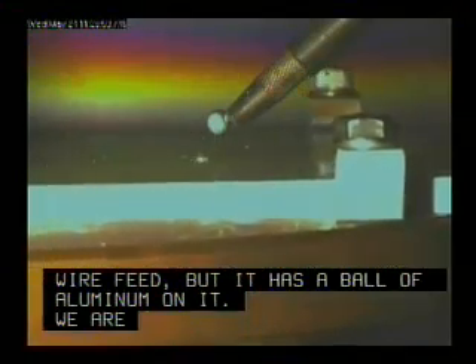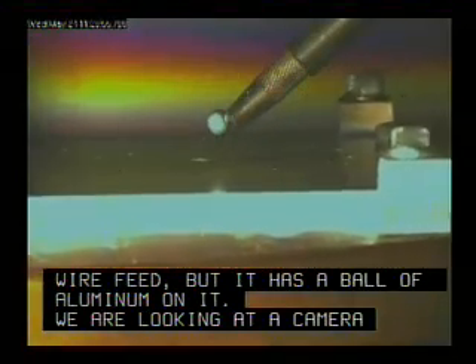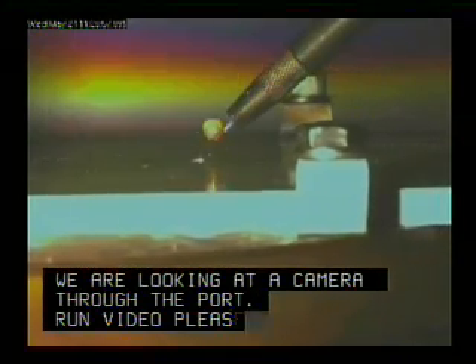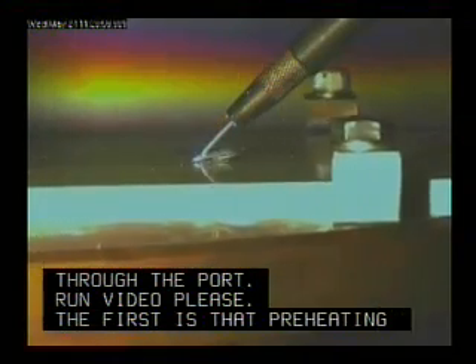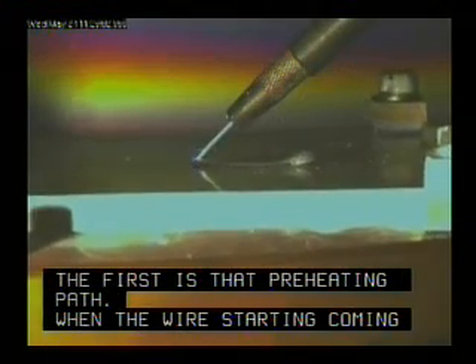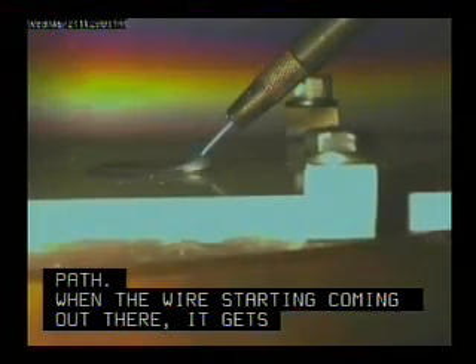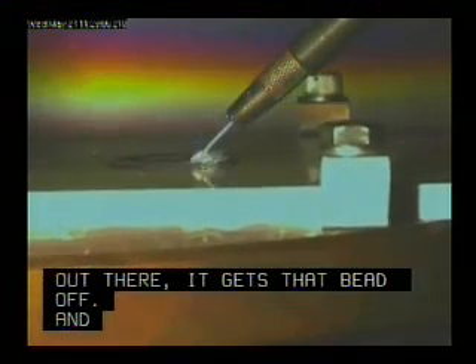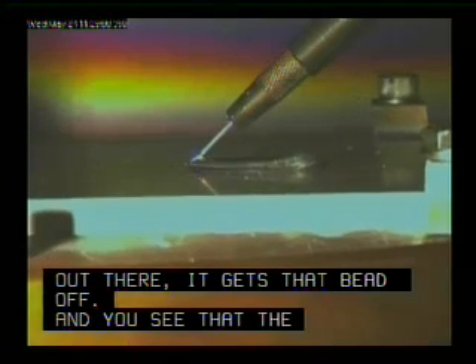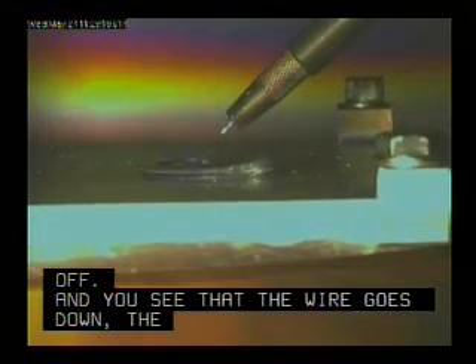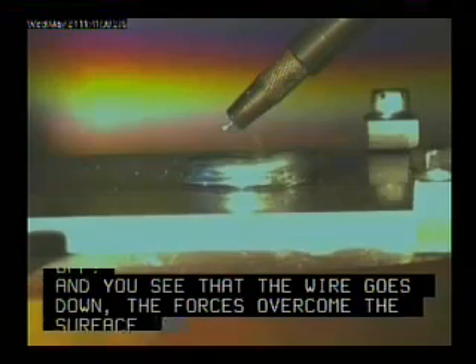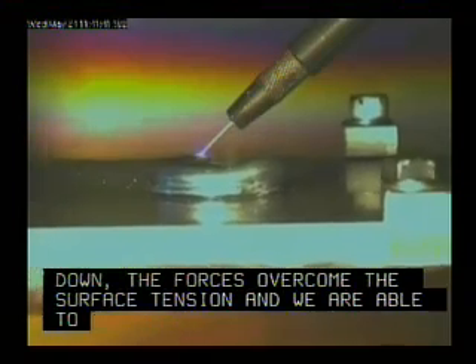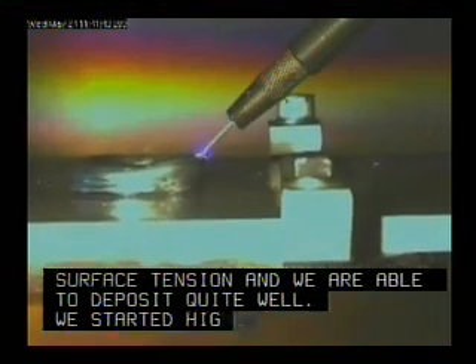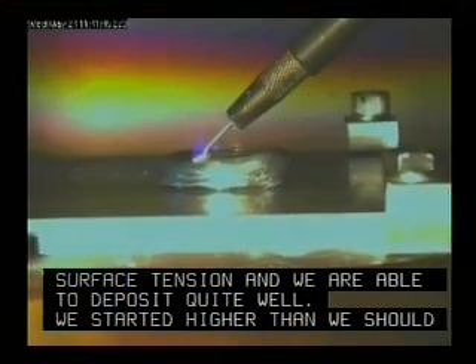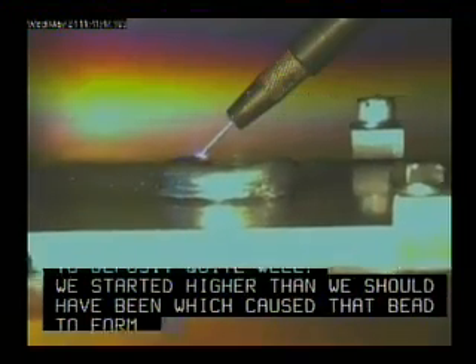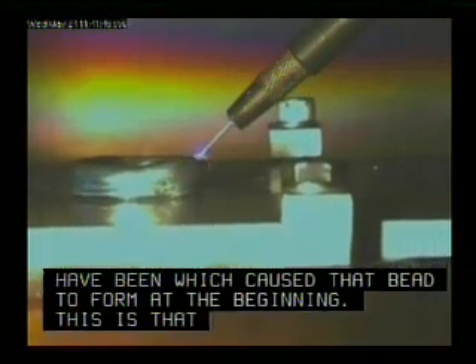The first pass, again, is just that preheating pass. When the wire starts coming out there, it shoots that bead off. And you see that the wire goes down, the wetting forces overcome the surface tension, and we are able to deposit quite well. We started a little higher than we should have been, which caused that bead to form at the beginning. This is that same circle now about 8 layers up, and it looks just like on Earth.